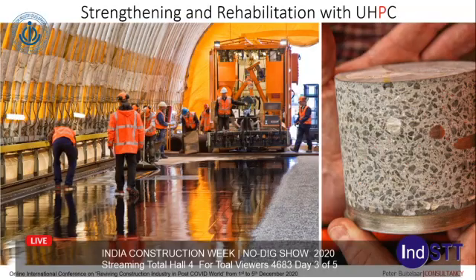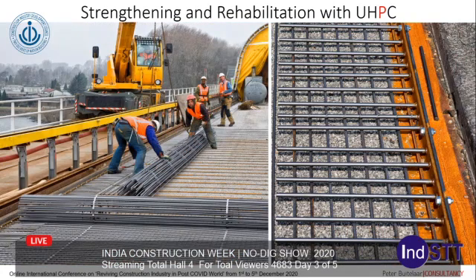This method turned out to be the use of a two-component epoxy-based adhesive with sprinkled-in bauxite aggregates. This resulted in a very good durable bonding strength of 4.8 megapascal and even 12.5 megapascal bonding strength in shear. Before applying the bonding zone, edge details were glued on the steel deck plate. After applying the bonding zone, the reinforcement is placed on rebars as spacers.